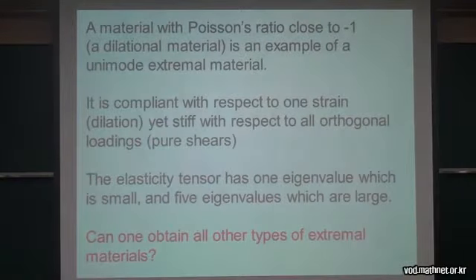So a material with a Poisson's ratio close to -1 is the extreme example of a material with low bulk modulus and high shear modulus. It's an example of what I call a unimode extremal material. It's compliant with respect to one strain, dilation, yet stiff with respect to all other orthogonal loadings, namely all shears. In elasticity in 3 dimensions, the elasticity tensor is represented by a 6x6 matrix that links together the stresses with the strains. For this particular material, the elasticity tensor has 1 eigenvalue which is small and 5 eigenvalues which are large.